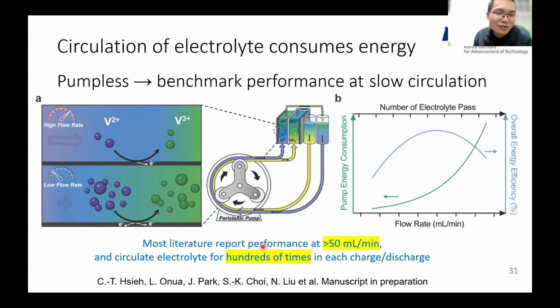And the more energy you consume, the lower the round trip energy efficiency of the flow battery is. So if you want the battery to be pumpless, then you want to circulate for as few times as possible. You don't want to circulate the electrolyte too fast, right? As slow as possible. And eventually, you can use gravity to slowly flow this electrolyte. So that reduce the energy consumed in the circulation.